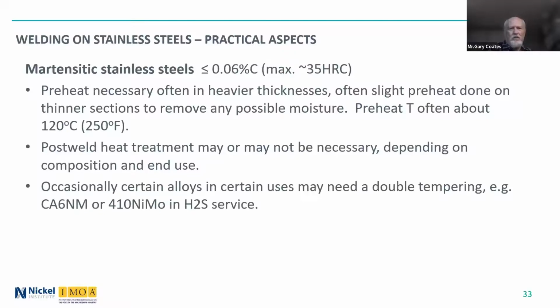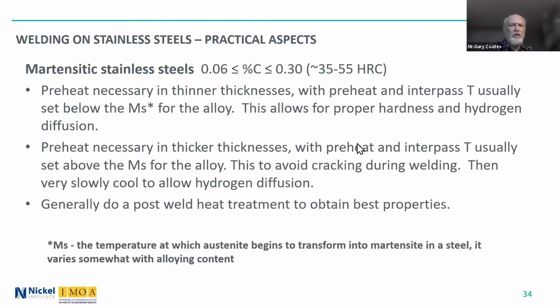Obviously, you want to try to avoid it, but it may be necessary. Most of the time, they can get away without doing post-weld heat treatment. And for certain alloys and certain uses, especially in hydrogen sulfide services, you might need to do a double tempering operation. So you temper it at one temperature and then temper it again at a slightly different temperature. The intermediate carbon levels, of course, as the carbon goes up, the hardness will also go up.